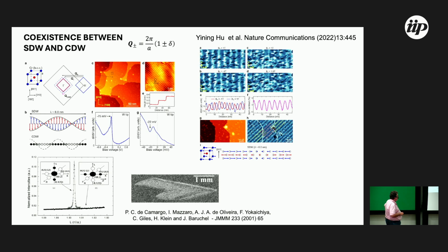In other experiments in the same paper, we observed this point at 1.6, 0.9 and 9.1. This is a peak of the charge density wave observed in Campinas, at LNLS. This peak is observed in all directions. This is an indication of a single domain of the charge density wave, and as a consequence, a single domain of the spin density wave. When we applied a magnetic field parallel to the surface of the sample, the charge density wave changed from perpendicular to parallel to the surface. At this point, no peak was observed when performing the X-ray in the same direction. This is an indication of the single Q state on the surface of the chromium.